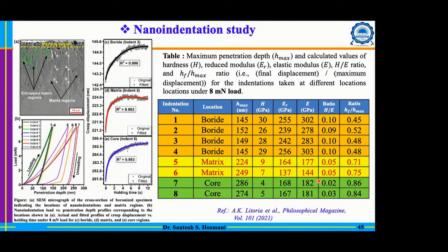That means even though that boride is stiffer, it still has the capability to absorb the lattice mismatch elastically. That's why, if you look at the adhesion test, the adhesion test confirms that this boride has very good adhesion. So there is no issue of crushing or detachment of this boride during application. That is unlikely to happen. So that is the best information we got from this.